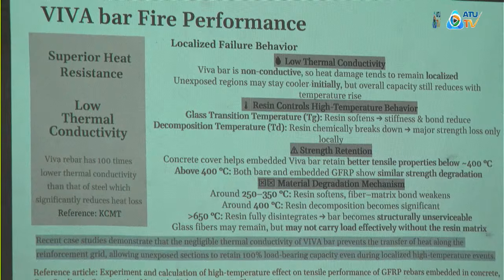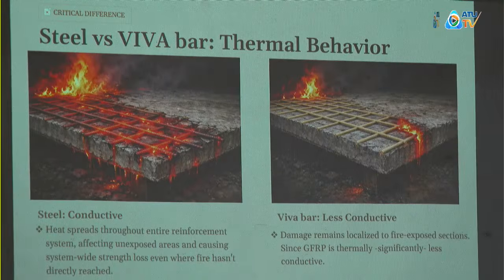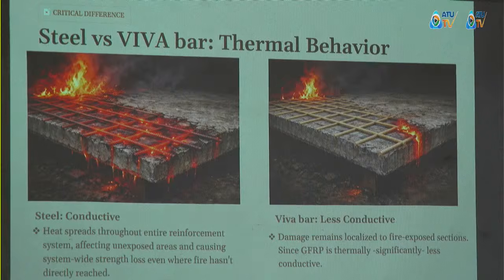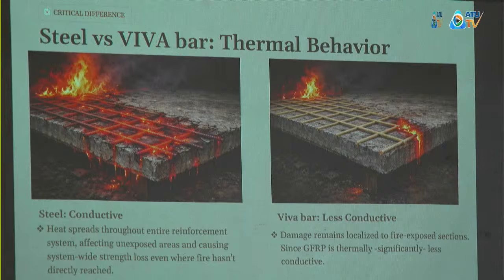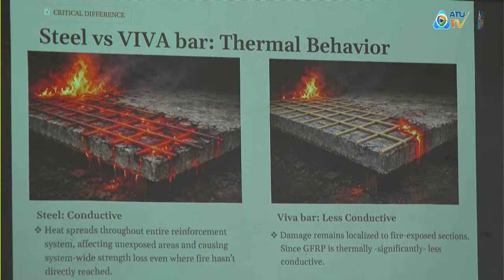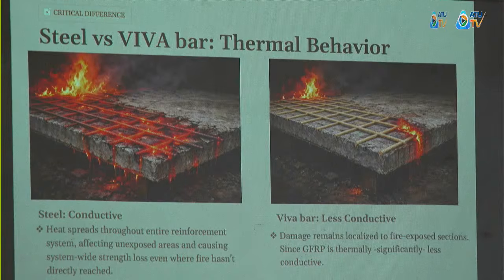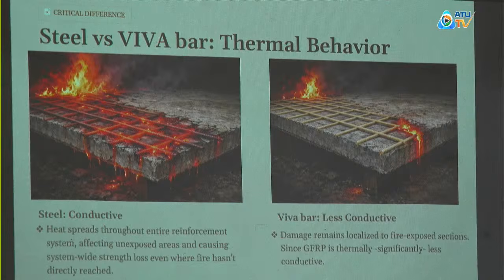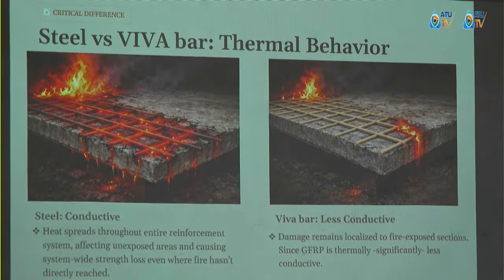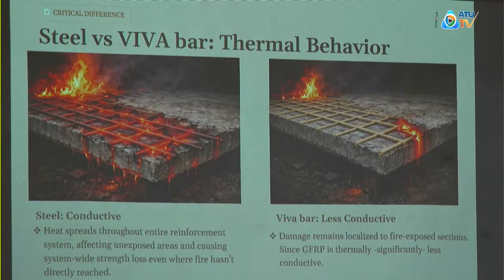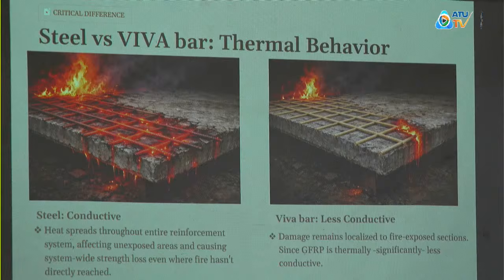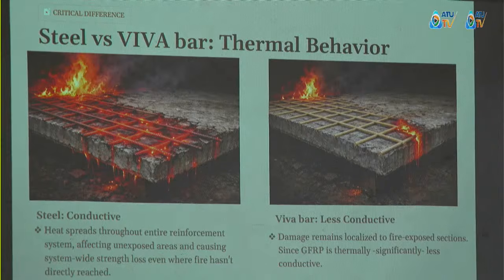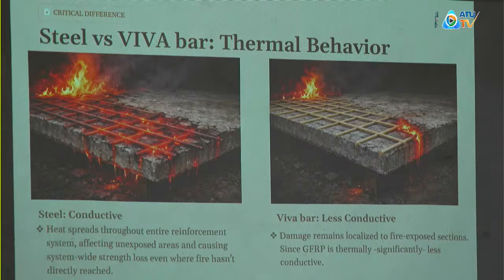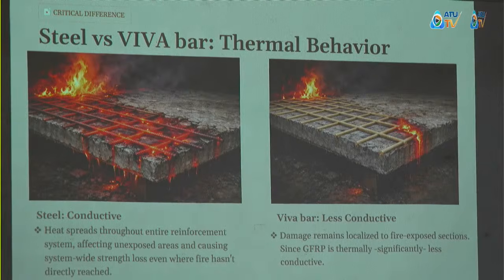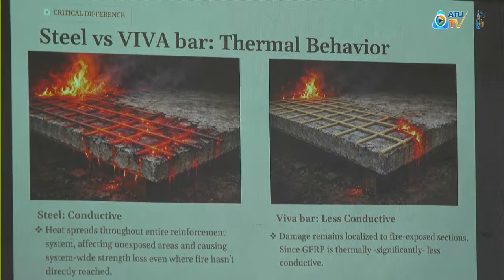Now, the next slide is what I was drawing from the fire analysis of steel and Viva bar that I have done, because this slide highlights one of the most important differences between steel and Viva bar on thermal conductivity. Steel is highly conductive, and once exposed to fire, the heat spreads rapidly throughout the reinforcement network, and it increases the system-wide thermal degradation. Because of the 100 times less conductivity according to the KCMT article, this heat remains more localized. For instance, if one part of the slab is experiencing the fire exposure, there is no conduction that would lead to heat generation in a system-wide nature.